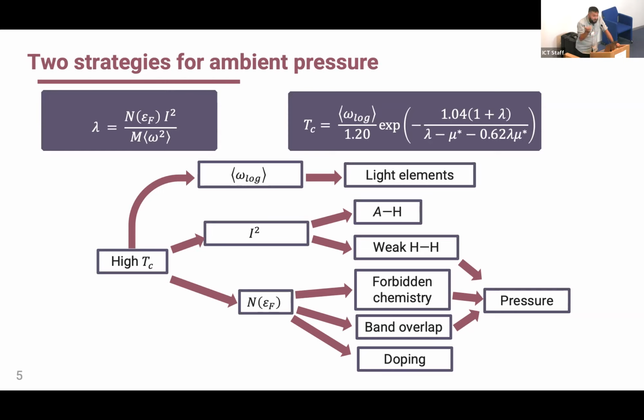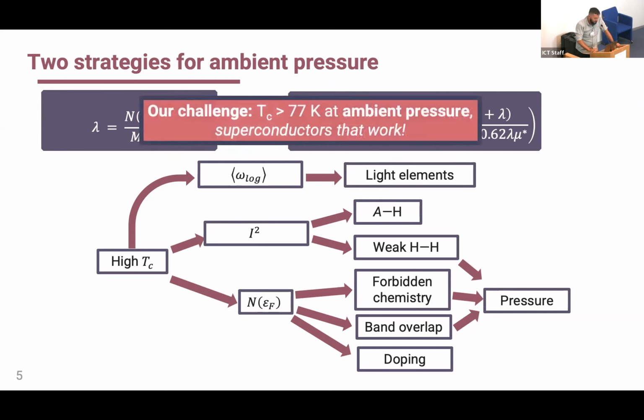which gives us a structure which is intrinsically metallic, but this, of course, requires pressure. We can get to metallicity by band overlap, which again requires pressure, or we can get there by doping, which does not. So in our research group, we have been focusing a lot on reducing the stabilization pressure. So we tried to set ourselves a reasonable goal, which is to achieve a TC higher than 77 Kelvin at ambient pressure. And we named this goal the superconductors that work.